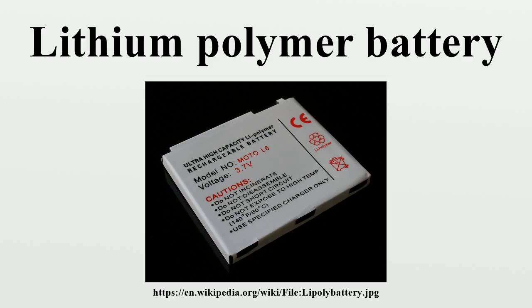As of the beginning of 2013, LiPo packs of 1.3 Ah exist, providing 45 C continuous discharge, and short-time 90 C bursts. Bigger packs of 4.5 Ah may feature discharge rates of 70 C, with 140 C bursts. LiPo packs also see widespread use in airsoft, where their higher discharge currents and better energy density compared to more traditional NiMH batteries has very noticeable performance gain. The high discharge currents do damage the switch contacts due to arcing, so it is advised to either use a solid-state MOSFET switch or clean the trigger contacts regularly.